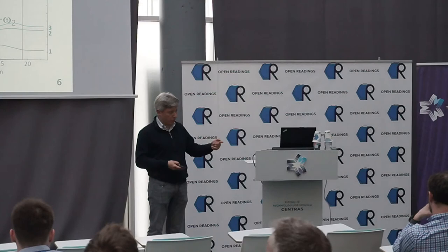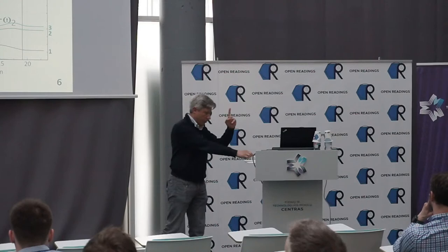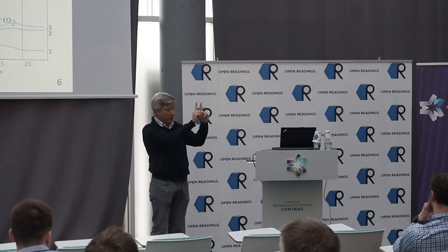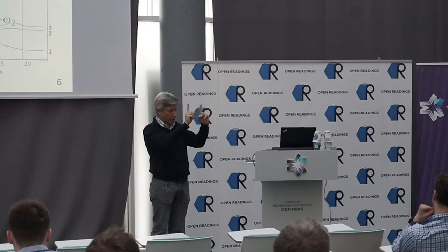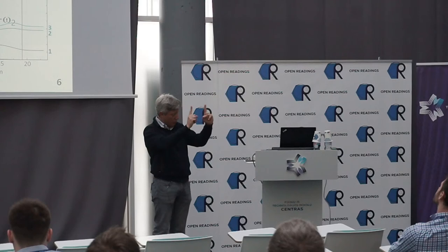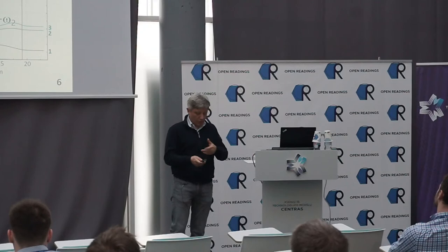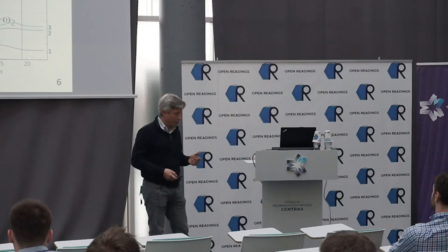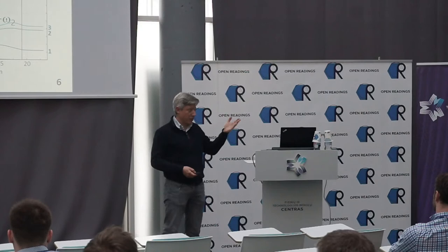So if you fix one of the wavelengths of our mid-IR laser and heat up the other laser, it will redshift. That means that difference frequency is reduced. Then we can keep this laser at the same temperature as it is, and temperature tune the other one. It will go the other way, and our difference frequency tunes to the blue. Now, QCLs can be temperature tuned in mid-IR by, let's say, 5 wave numbers, maybe 10 wave numbers. 10 wave numbers is 300 gigahertz. So you can build a broadly tunable source in this way.